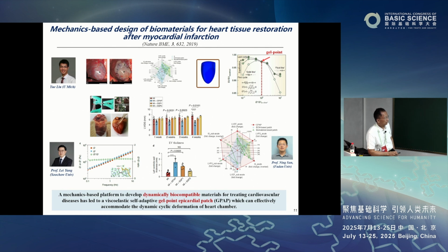Okay, so we were able to use simulations to identify a specific material called a gel point material, a polymer-based gel point material that's in between a solid and a fluid. This is the ratio between storage modulus and loss modulus. For a solid, you have basically storage modulus but no loss modulus, for a purely elastic material. For a fluid, you have loss modulus but no storage modulus. But when the two moduli are equal, the ratio equals 1, that's the gel point. That's halfway between a solid and a fluid. It's not a solid, not a fluid, but halfway in between. That's a viscoelastic material. So we identified this as the best material to treat myocardial infarction.